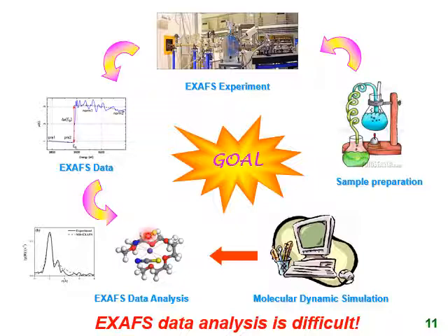However, for this polymer salt complex, it is very difficult, as the polymer electrolyte sample is not only amorphous but also has a very high degree of mobility, because ions can diffuse and the polymer chain itself is quite mobile, since the glass transition temperature of PEO is quite low, less than room temperature. So everything is very dynamic. So we propose to construct the model using MD simulation and use several snapshots from the MD trajectory to predict the EXAFS spectrum, not the fitting like people in the experiment try to do.